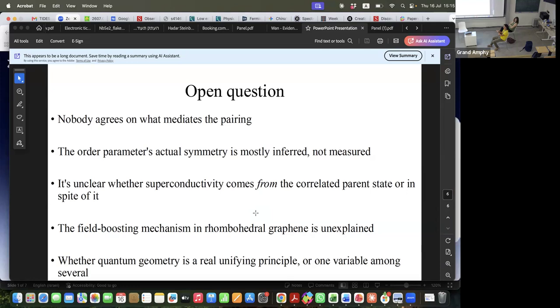Supercurrent from S-wave to P-wave is supposed to be zero. Exactly. Unless your scattering in between is complicated. But there's a methodological problem with this proposal: if the mechanism is strongly related to electron-electron interaction, by placing a superconductor nearby, you're screening these interactions. It's not so trivial that what you measure is actually the system, identical to the standalone system. The other component will also be screened because there is always an interaction. So that's a challenge if you want to do this.